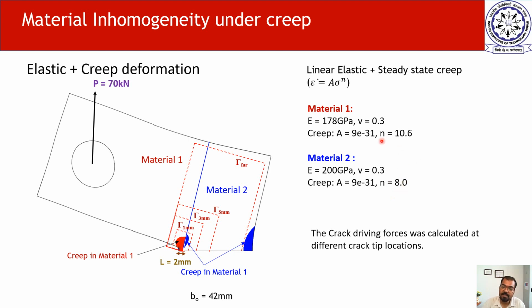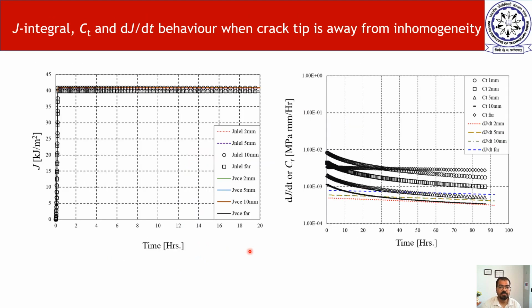That means the creep strain will be more in material 1 in comparison to material 2. So for this situation we calculated the J integral, and you see in the first step this is the point where the loading is happening, and after that we keep the force constant, and you see that the J integral calculated from Abaqus is exactly equal to what we get from the configurational forces, because our creep zone is small and all the contours are encompassing the creep zone. And this is for one particular model.